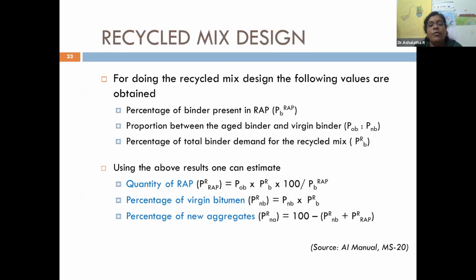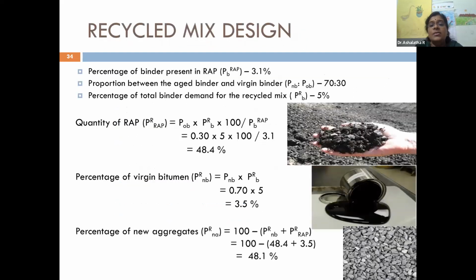Then, for doing the recycled mix design, we have to find out the percentage of binder present in the RAP, the proportion we already obtained, and the percent total binder demand for the recycled mix. We use the above expression, given in Asphalt Institute Manual MS-20, to find the quantity of the RAP, the percentage of virgin binder, and the percentage of new aggregate. Those calculations were done.